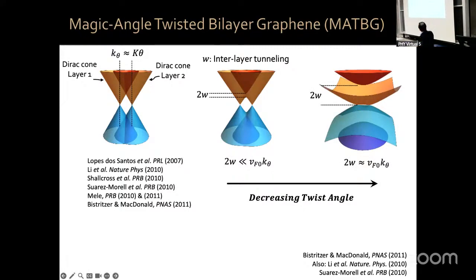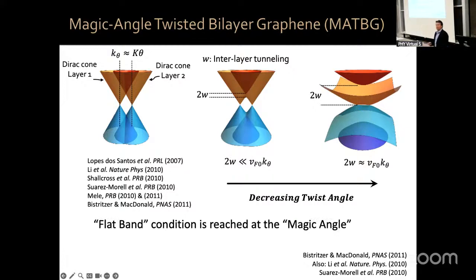When that happens, we say that a flat band condition has been realized or reached. The angle corresponding to that flat band condition is the magic angle. It was coined the magic angle by Bistritzer and MacDonald, and that happens to be 1.1 degrees for graphene on top of graphene.